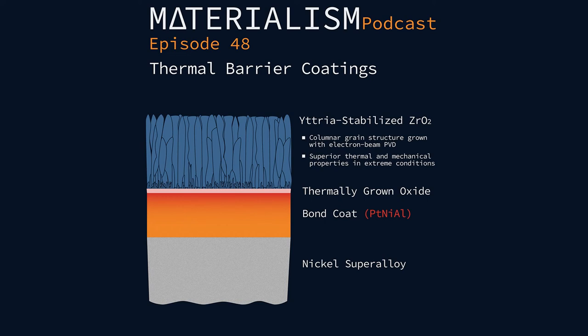And when you give it a crack nearby, since the tetragonal to monoclinic transformation, monoclinic being the stable phase, when that happens, it actually expands volume a little bit. Oh, so it puts that crack in compression then. Bingo. It puts sort of a closing stress on the crack. And so for applications where you're trying to prevent cracks from growing, that's really awesome. But for one thing, remember here, this is already full of cracks. These things have a pretty defective structure.